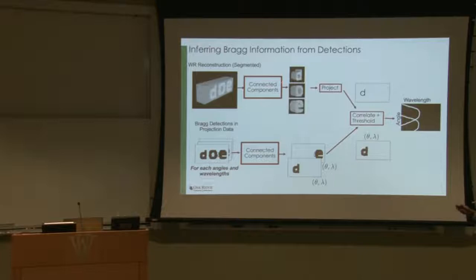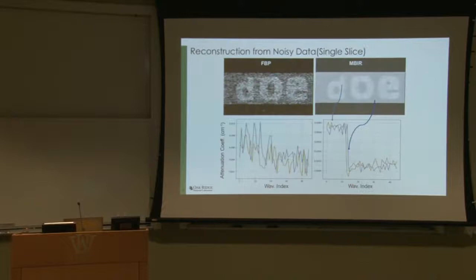You can get a hyperspectral reconstruction, do a connected component analysis, segment the components, and then correlate each of the components with the measurements identified as anomalous, and then you can get this crystalline signature also. Let's look at some results now. If I look at a simulated noisy data set and I apply a standard technique based on the analytic inversion, you can get a lot of noise in the reconstructions. Whereas with these model-based approaches, you can get significant improvements in the reconstruction quality because it's a nice trade-off between noise and resolution, which you cannot get with the standard techniques for just noisy data.